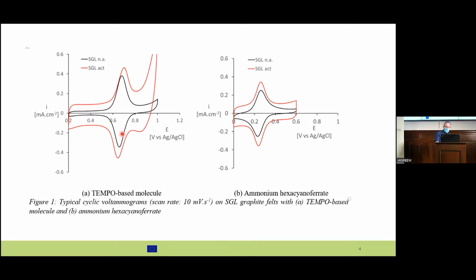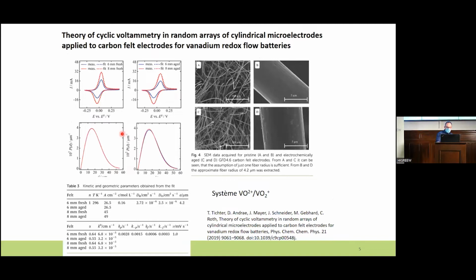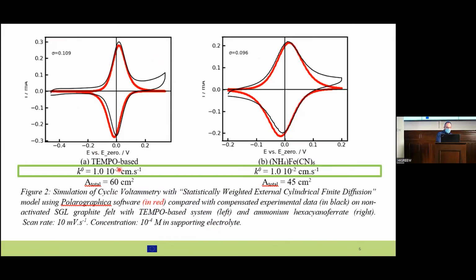Is it true? So we went further, and we analyzed this kinetic with a model given in the literature. The kinetic that is extracted here, in this condition, perhaps not perfect, but it is very high, higher than 10 to the minus 2 centimeter per second. So 10 times higher than the target we have in HIGREEW. So this is great, this is good news. We reached the target from the beginning of the project, I would say.